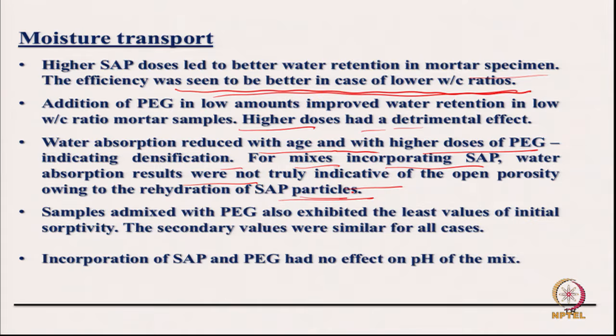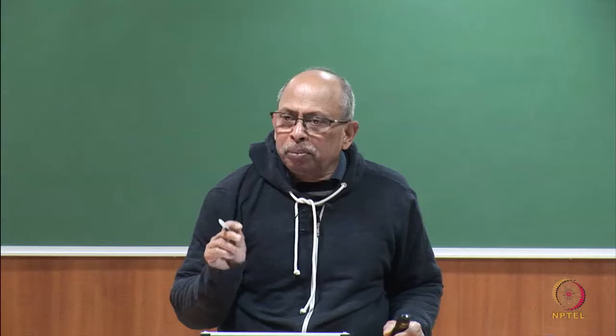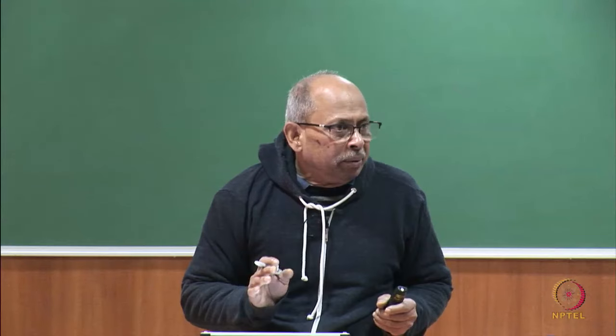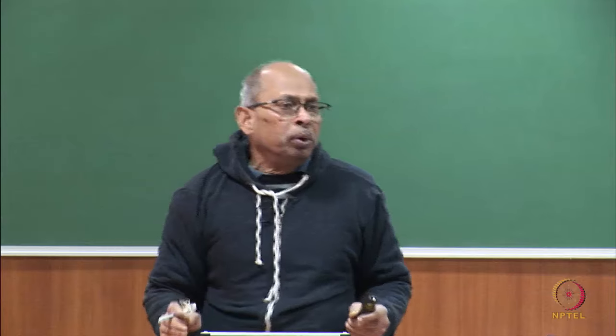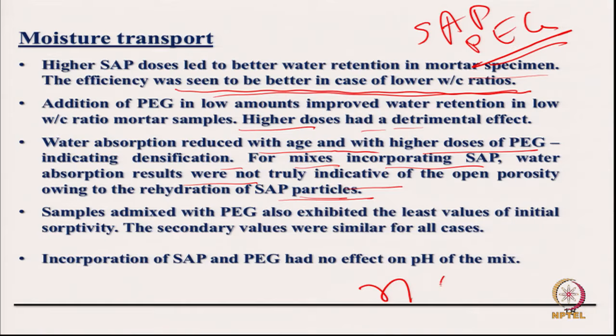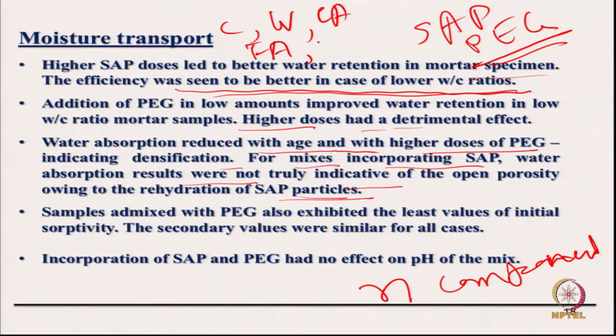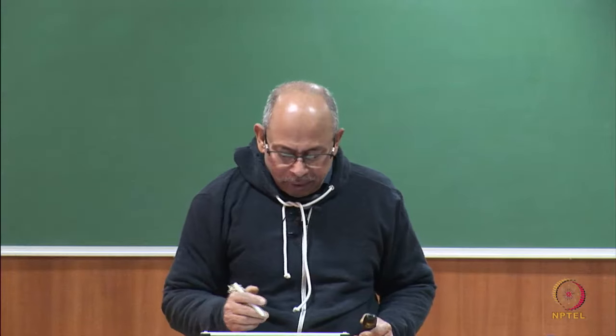So, the point for your class, what I would suggest, is essentially that these materials are available, super absorbent polymers or PEGs, which are curing admixtures. You have to use them, as we said, with the dosage optimized and all properties checked before using, because this has not come to such a level that you can use it without that. So, it has to be an engineered concrete. That is why I was talking about N components of concrete, not 4: cement, water, coarse aggregate, fine aggregate, X1, X2, etc. Different varieties of admixtures are possible, and you have to design the system for sustainability and for the performance that you require.